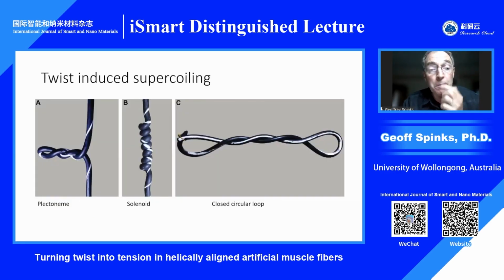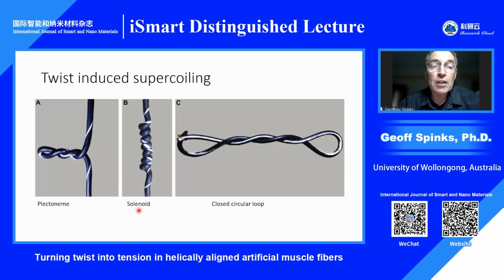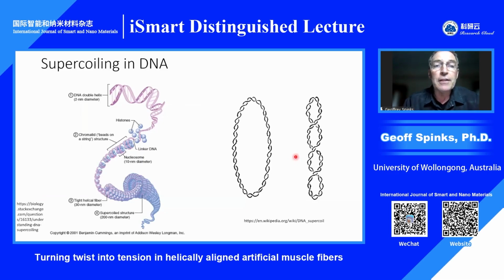Now, there's different types of supercoils. We have the plectoneme here on the left. That occurs at low tension in the fiber. At higher tension, if you keep on inserting twist, then you'll produce these solenoid type supercoils that are stacked neatly on top of one another. And in fact, that's the process we use to over twist the fibers to produce the twisted and coiled artificial muscles. If you twist the fiber and then join it into a loop and let it go, it will ply on itself to produce these type of circular loop structures. Now, what's really exciting, in fact, is that all of these structures exist in nature.